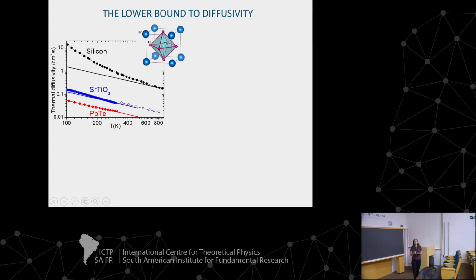So now I want to turn to the high temperature part of STO, that also at the time gave us some evidence to think about. Actually, this is the same measurement that I have shown before, but this is just reported for the high temperature part and in terms of thermal diffusivity. So diffusivity is the physical property that governs the heat equation, is the ratio of the thermal conductivity to the specific heat.